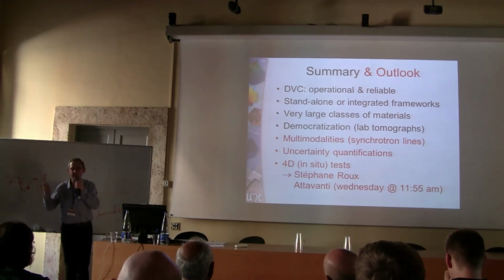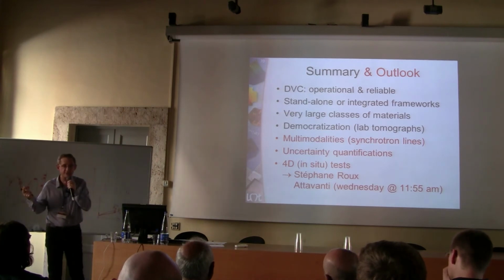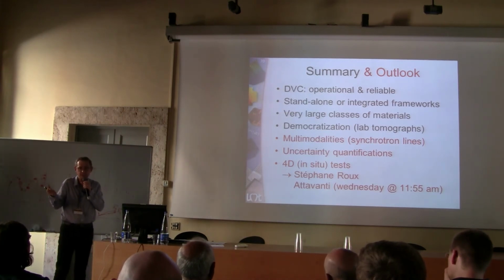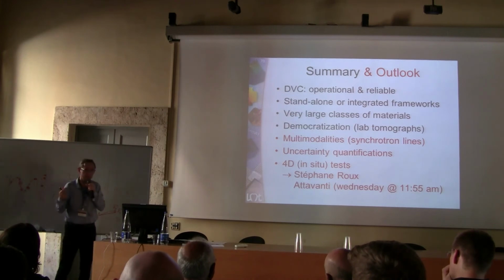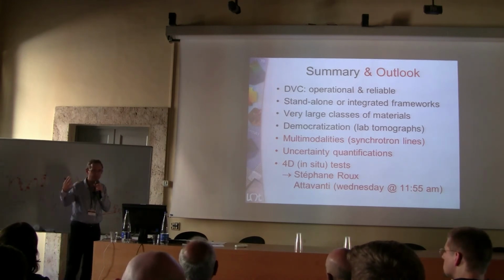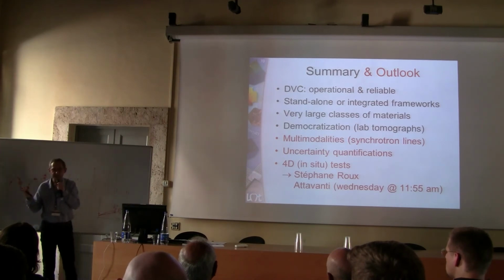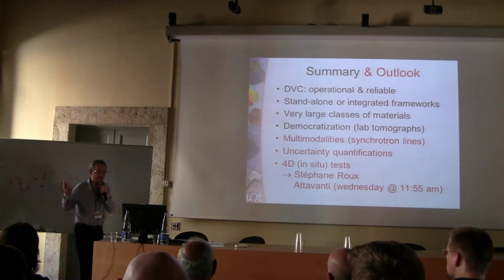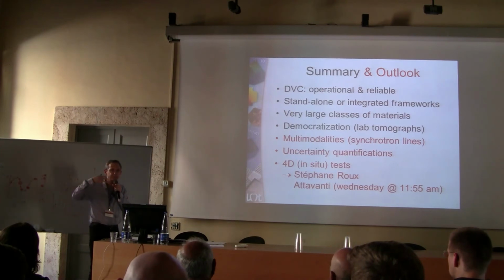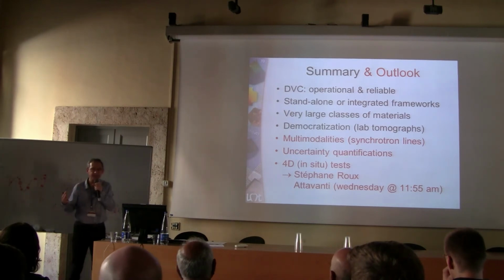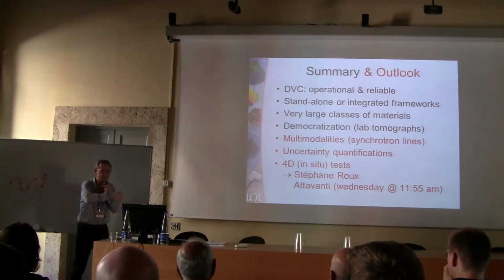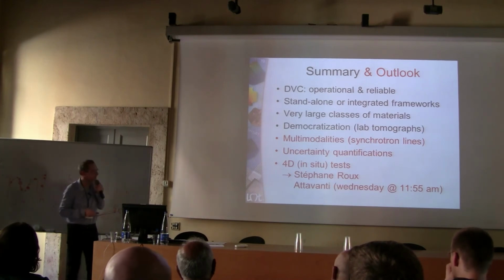But hey, wait a second, we are measuring displacements with DVC, right? So if you were able to combine the reconstruction and kinematic measurements, that means you would be able to basically acquire on-the-fly radiographs and then perform a full 4D analysis to extract your kinematic basis or material parameters.